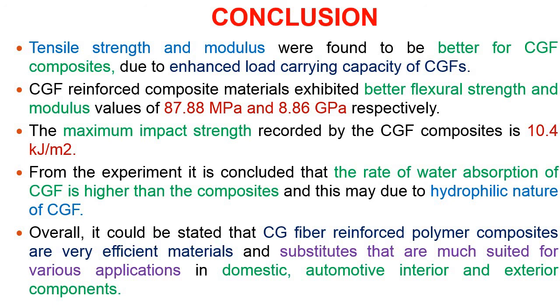Tensile strength and modulus were found to be better for the Calotropis gigantea fiber composite due to the enhanced load carrying capacity of the Calotropis gigantea fiber. Second point, the Calotropis gigantea fiber reinforced composite material exhibited better flexural strength and modulus values of 87.88 megapascal and 8.86 gigapascal respectively. Third point, the maximum impact strength recorded is nearly 10.4 kilojoule per meter square. And from the experiment it is concluded that the rate of water absorption of Calotropis gigantea fiber is higher than the composites. This may be due to the hydrophilic nature.